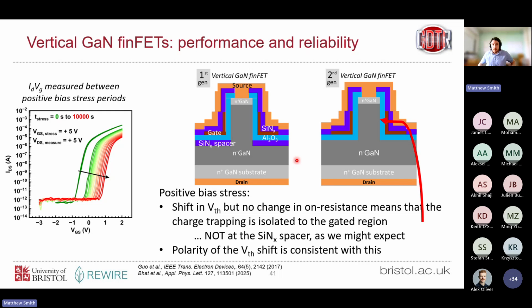A really interesting result was that we would maybe expect, there's a mistake here, this should be the second generation design, this is the first generation, but we might expect that adding this silicon nitride spacer layer here is what's caused the change in threshold voltage shift. So we might expect that it's trapped charge in this region. That's initially what we suspected. But from simulations, we found that if you include a bunch of fixed charge, or trapped charge, in this region, it doesn't give you this type of characteristic. It just degrades your on current a little bit, because you're essentially squeezing the fin.